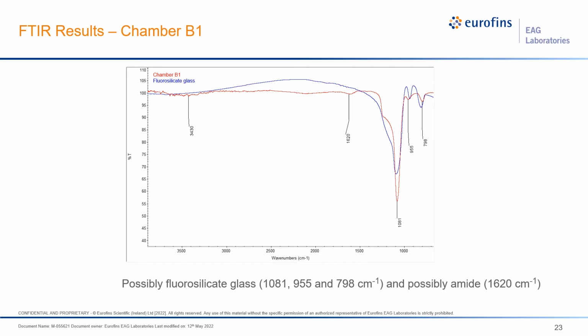The next thing is the next lab. This is chamber B1, from a different lab. What we see here is fluorosilicate glass. So maybe something has happened with the wafer. It was heated, maybe a little bit of oxide came on the surface. And then the peak at 1620 is due to an amide.